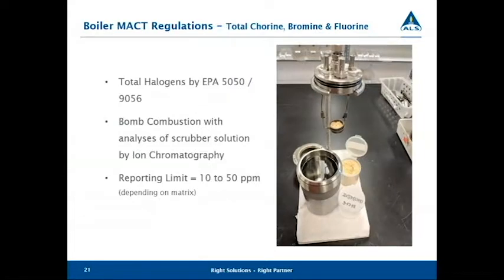Another test that we do for the Boiler MACT regulations is total halogens and primarily total chlorine. This is an older method that involves combusting the sample in an oxygen bomb. The sample's weighed out. There's a small amount of scrubber solution put inside the bomb. The bomb is closed up, sealed, and then it's charged with 30 atmospheres of oxygen. You can't really see it very well, but there's a fuse wire that goes from the two electrodes into the sample. And the sample's combusted, and any chlorine or halogens in that sample are going to turn into a gaseous form. They're going to be absorbed by the scrubber solution.